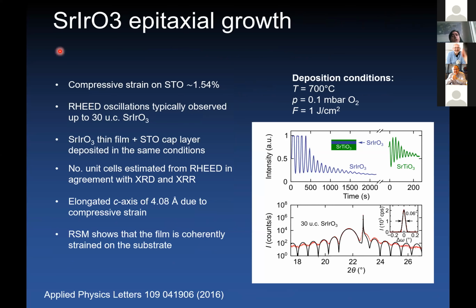And the difficulty is that the iridate materials are extremely complex to grow. Since you're dealing with a very large B cation, it is hard to obtain films with a correct stoichiometry of the system. And it's very hard also to prepare a target that is able to support a PLD growth process correctly and that contains the correct stoichiometry. So this was also a strong collaboration with chemists that helped us to synthesize a target with an appropriate iridium stoichiometry. But after a lot of work, we succeeded in obtaining very high quality strontium iridate thin films.